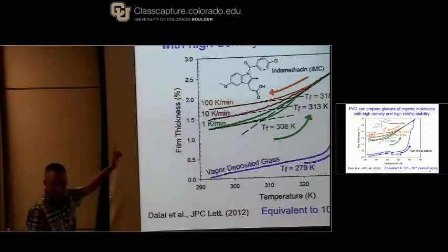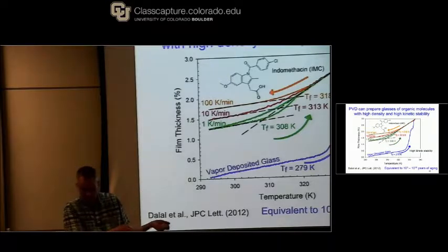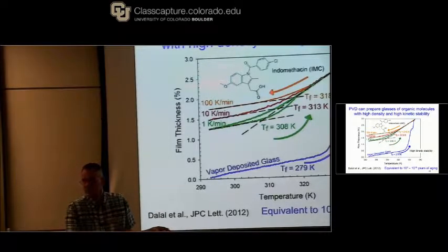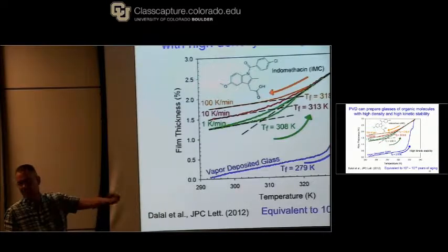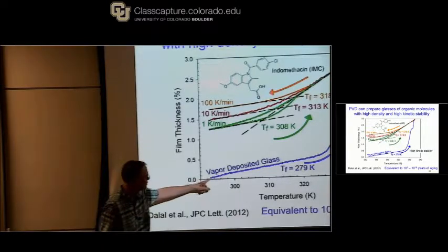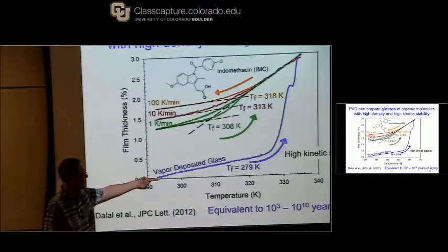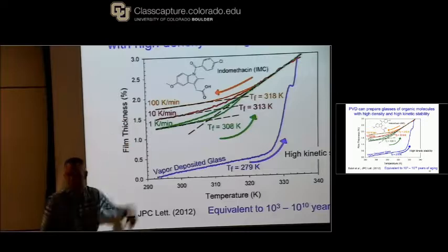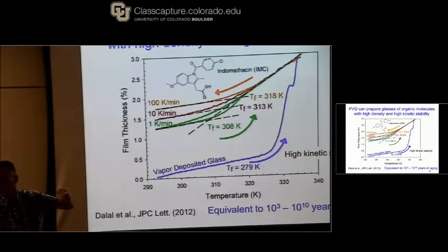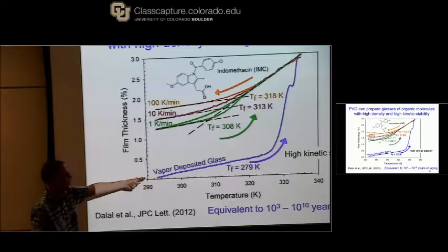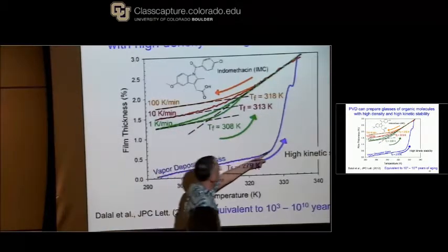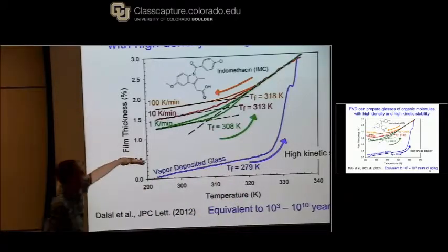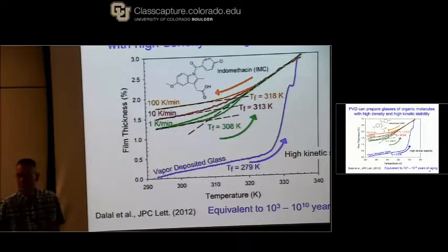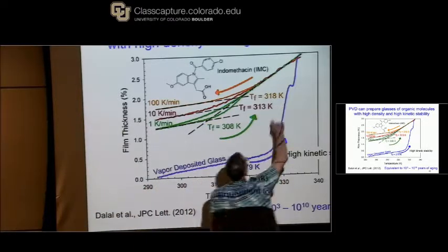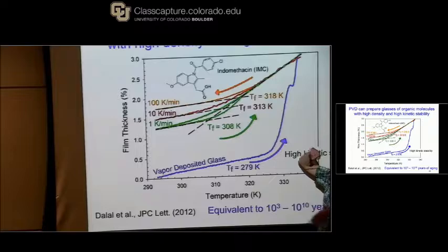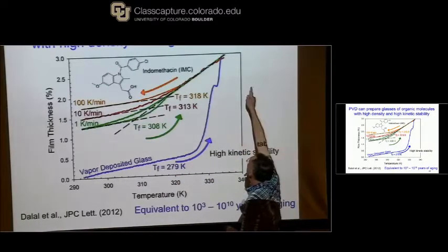We take the film off and we take it to an instrument called a spectroscopic ellipsometer, which does a very sensitive measurement of the thickness of the film. And this is room temperature. So I take the film, I put it on the ellipsometer, I measure a thickness, and then everything else here is going to be reported relative to the thickness that I started with. So the experiment goes, I heat up the vapor deposited glass, I get to here, the thickness over a pretty small length of time jumps by 2 or 3%. I get up there, I now have a supercooled liquid. So it transformed from the glass into a liquid.